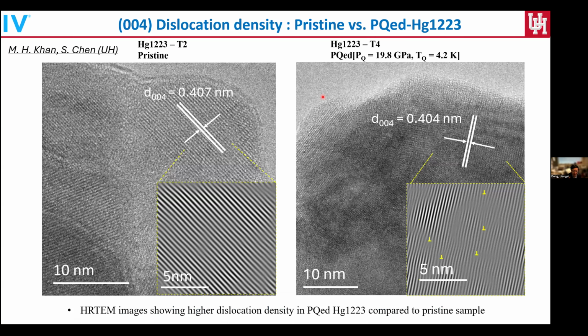Sometimes we have to do many pressure quenches to prepare a good enough sample to show this image that has high enough resolution to calculate the dislocation densities. So right now we're on the stage of mapping different locations. How does the dislocation density change? But one sentence summary is there is a clear indication that the dislocation density increases a lot after the pressure quench.